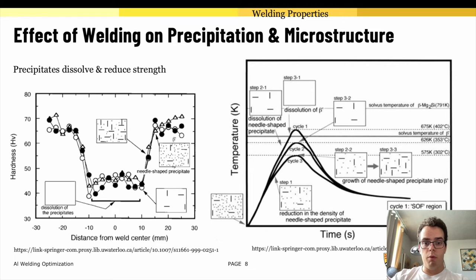This is a busy slide but we'll walk through it piece by piece. We can see that as we input heat from a welding process, we are effectively both melting the metal as well as the precipitates that we carefully formed for our 6000 series aluminum. On the left you can see a traverse of a hardness plot from the base material all the way through the weld material back to base material. You can see a significant drop of hardness values. This is mainly due to the changing microstructure in the actual welded material. Looking on the right we can see what's happening. As you input the temperature we're creating dissolution of all the precipitates that we carefully shaped within our aging process.